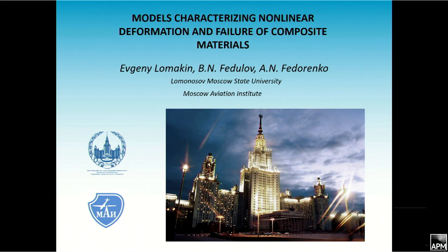Very often for many materials the stress strain curves are different for the conditions of uniaxial tension and uniaxial compression. But these two types of loadings are only two types among the infinite number of possible stress state types. If the deformation properties are different for these two particular types of loadings, it means that they are different for other types too. And we can't restrict ourselves to the consideration of these two particular types only. We have to introduce the corresponding parameter of stress type.